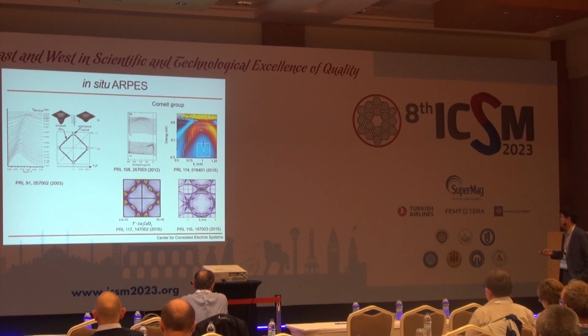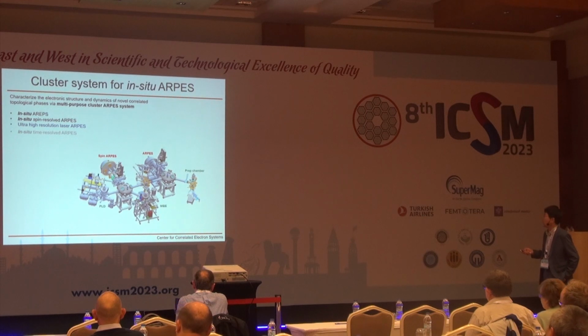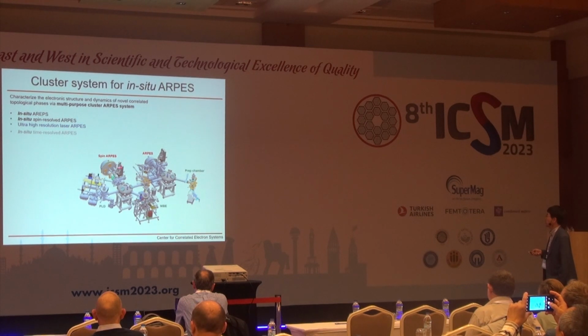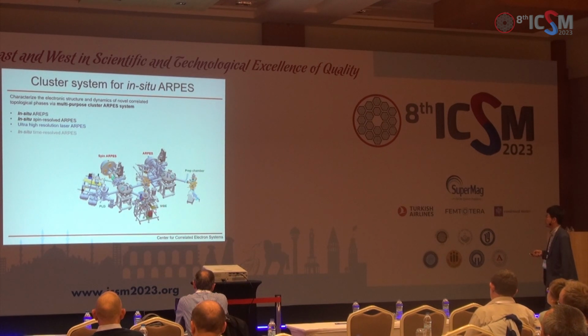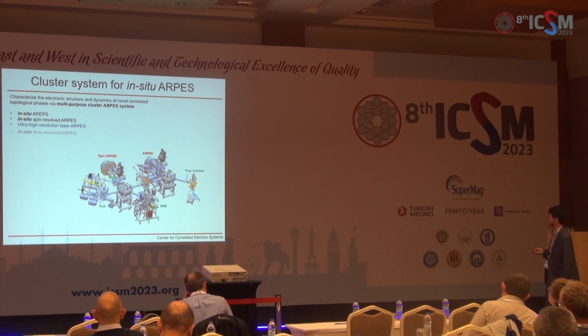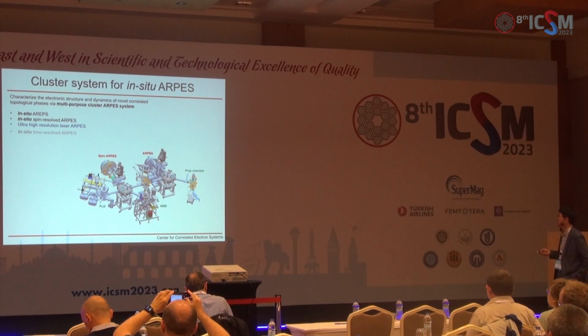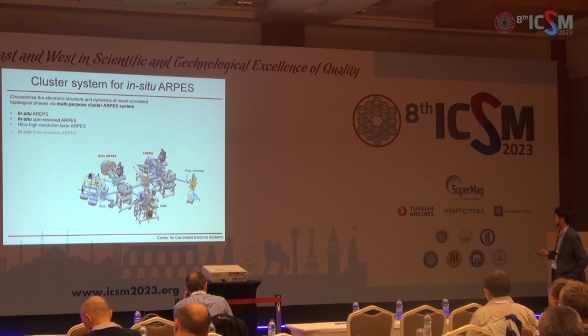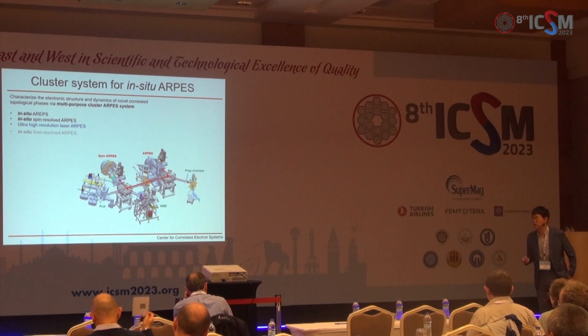Now, let me show you what we did from here. To do that, we have this cluster system for in situ ARPES. I have two ARPES systems, one equipped with a spin detector, and I have MBE for chalcogenide samples and films, and PLD for oxide films. And also, we can make some surface systems using a prep chamber that's equipped with a sputter annealing system. Using this chamber, we grow oxide films in PLD, MBE, and the prep chamber, and we transfer films to the ARPES chamber without exposing them to the air.